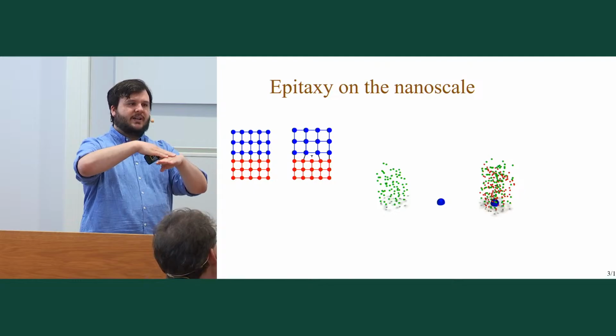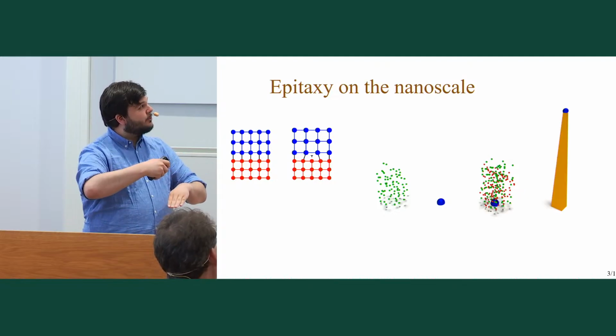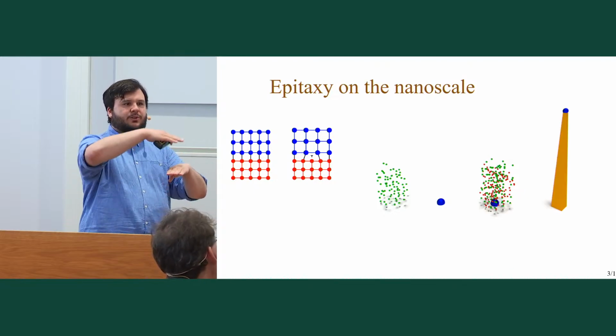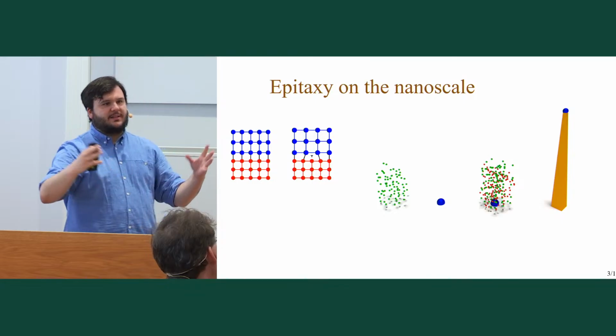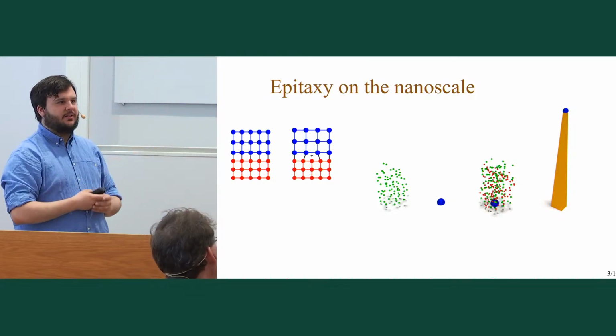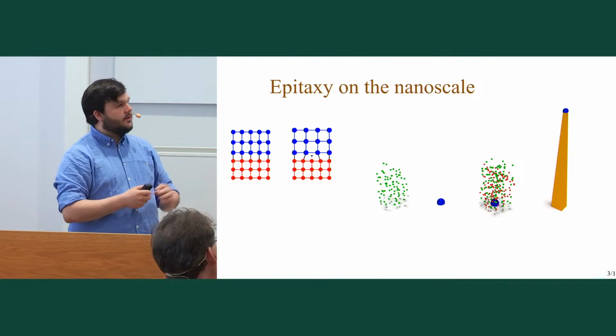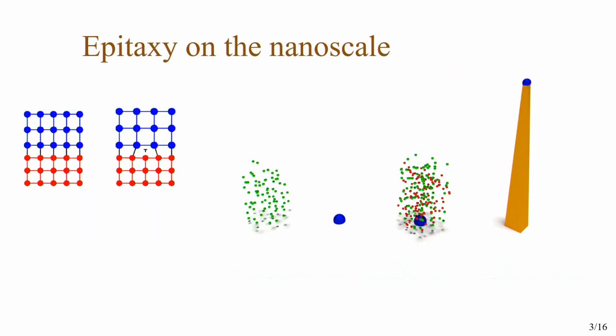And if it does so again and again and again, it will grow into this nanowire, because it will want to grow in the same direction and deposit the material at the same place every time. So that's how I would grow a nanowire using these catalyst particles. Then we have the vapor phase, which is the gas, the liquid, which is the particle, and the solid, which is our nanowire.